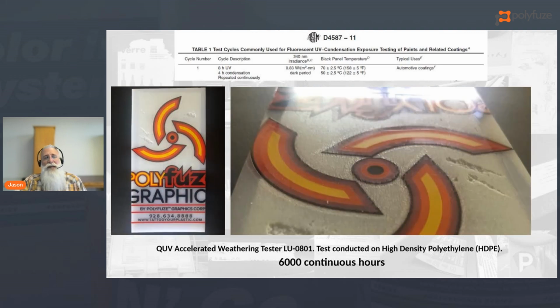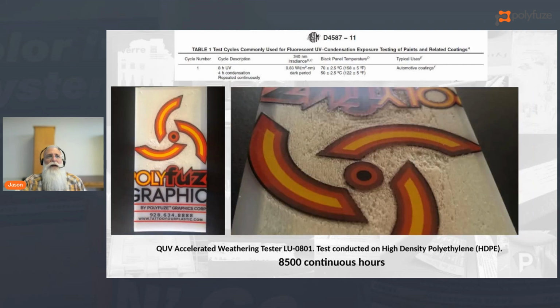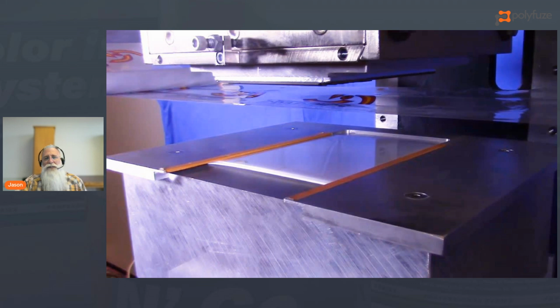6,000. Now you're starting to see the base material start to degrade. And then, of course, at 8,500 hours, total degradation of the base plastic. But it's always interesting to note that it's actually protected in the area where the label is just because of the UV stability of it. So how does this work, right?